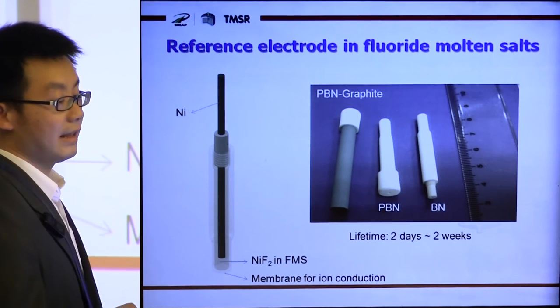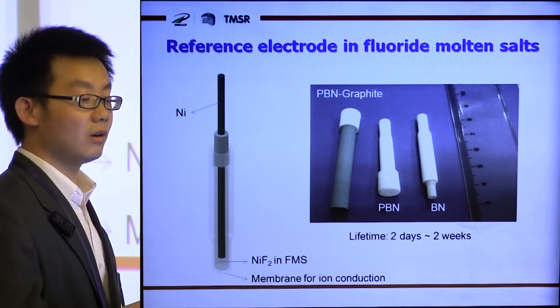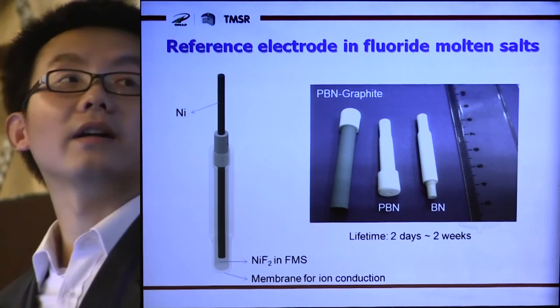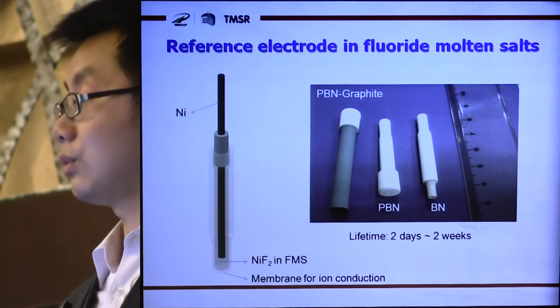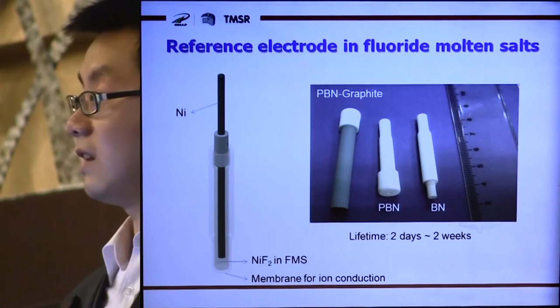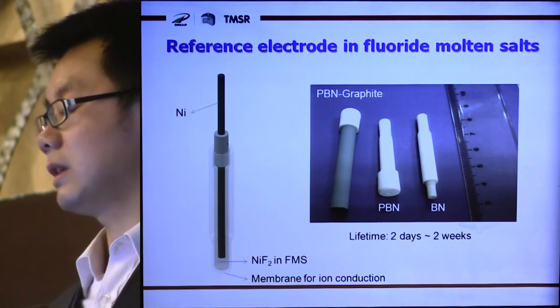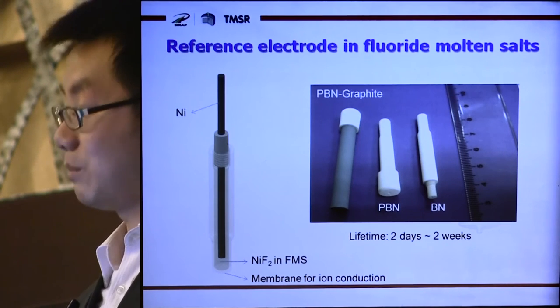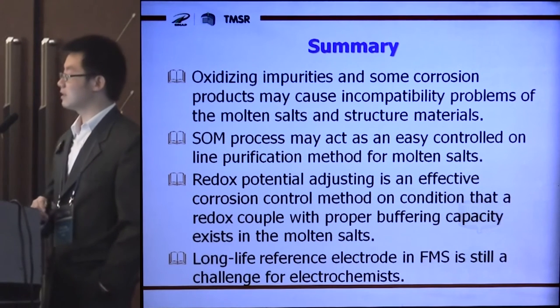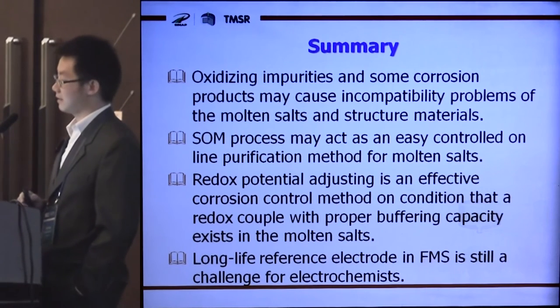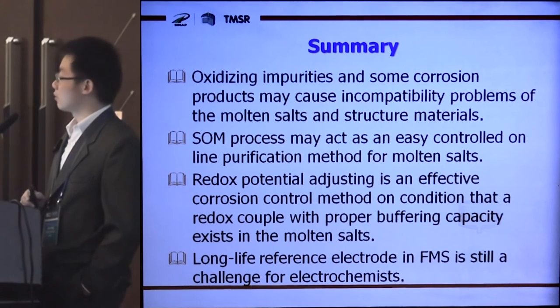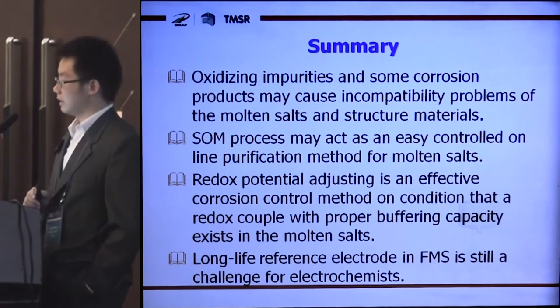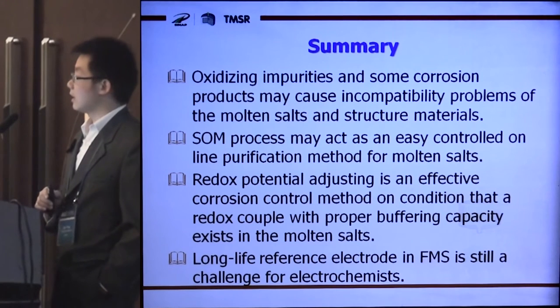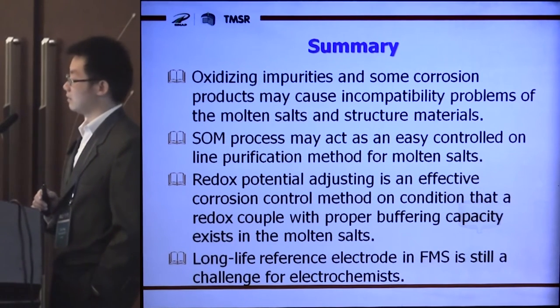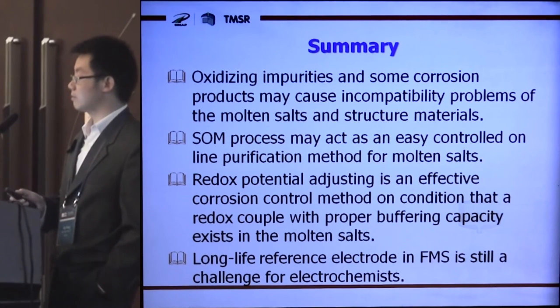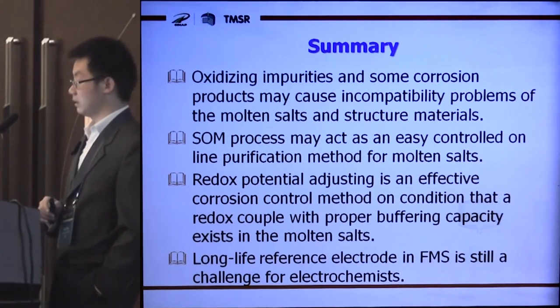These three reference electrodes were prepared in our laboratory, and their lifetime are about 2 days to 2 weeks. A long-life reference electrode in fluoride molten salts is still a challenge for electrochemists. Oxidizing impurities and some corrosive products may cause incompatibility problems of the molten salts and the structural materials. The SOM process may act as an easily controlled online purification method for the molten salts.